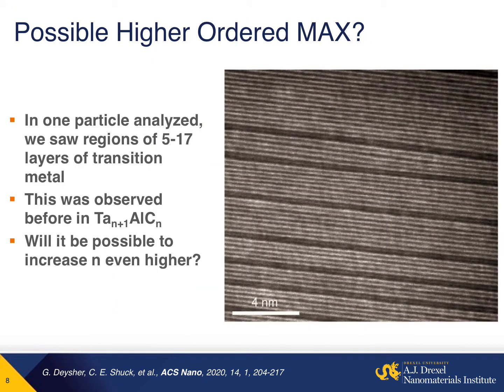Before we completely switch to MXene, I want to point out one other interesting thing we saw in this MAX phase. In one of the particles we analyzed with TEM, we actually saw these much larger stacks of layers. So this one particle seemed to have layers between 5 up to 17 layers of transition metal. We don't know if this was a unique particle with this, or if this is indicative of higher ordered MAX phases that can occur.